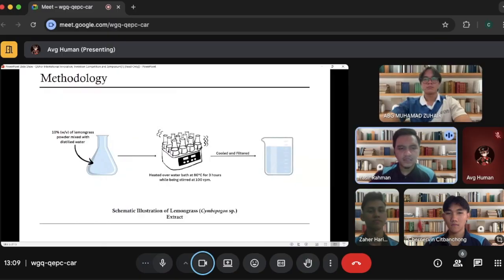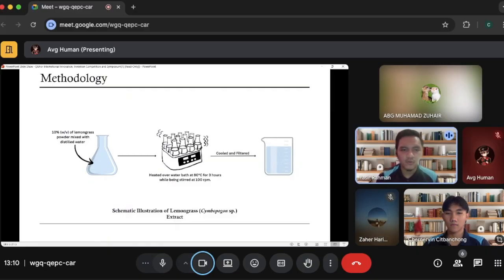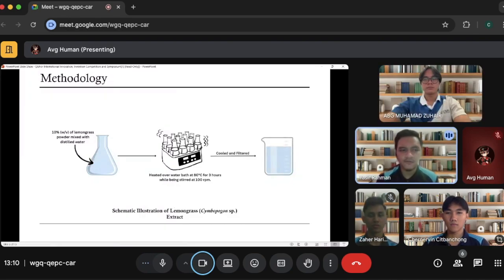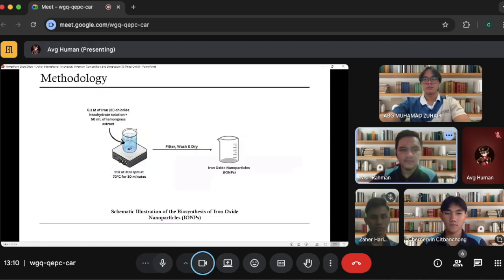Okay, moving to methodology. Let's look at the procedure for lemongrass leaves extraction. The lemongrass leaves were first picked, washed, cut, and dried under sunlight until achieving constant weight. The dried lemongrass leaves were then ground into powder form. 10% of the powdered lemongrass leaves were mixed with distilled water and heated over a water bath at 80 degrees Celsius for 3 hours with an agitation speed of 100 rpm. The extract was filtered and used as reducing and stabilizing agent during biosynthesis of iron oxide nanoparticles.